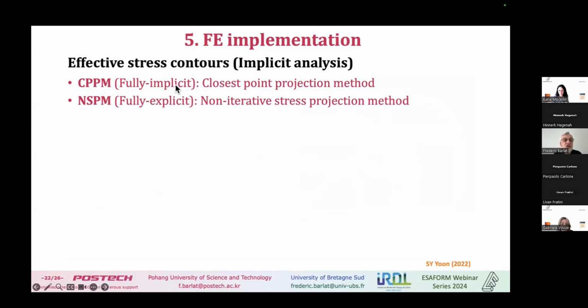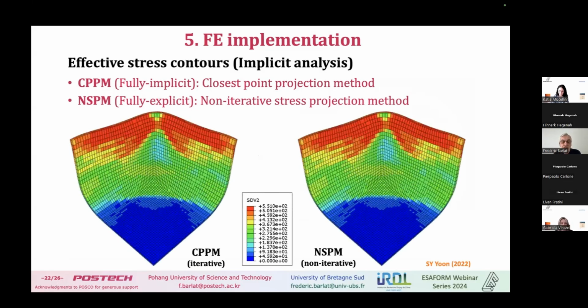So just to show, of course, it's difficult to compare, but if we compare the two methods, CPPM, fully implicit, and NSPM, fully explicit because it's only one step. So these are the two methods, and we represented the stress in different elements, and I think it was a square cup in this case. But if you look at the two, the stress in both cases is the same. Okay, maybe there's a very small difference, and it's almost impossible to see where the difference is. And actually, when we do the simulation with those two methods, we get the same results.